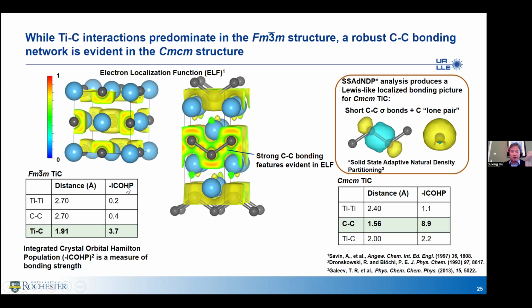If this number is high, in the Fm3m structure you can see the titanium-carbon bonding. TiC has the highest bonding. But when you get to this Cmcm structure, you can see the C-C bonding become extremely stronger. This number is like 4 times bigger than the titanium-carbon bonding. So what does that tell us? It tells us even in the solid, this titanium carbon structure already has this strong C-C bonding. So the question is, would that be a precondition for favorable diamond formation?